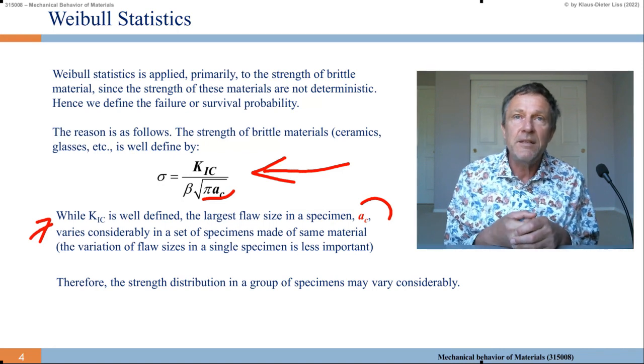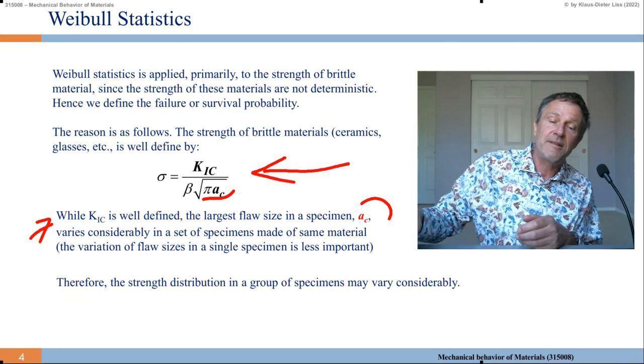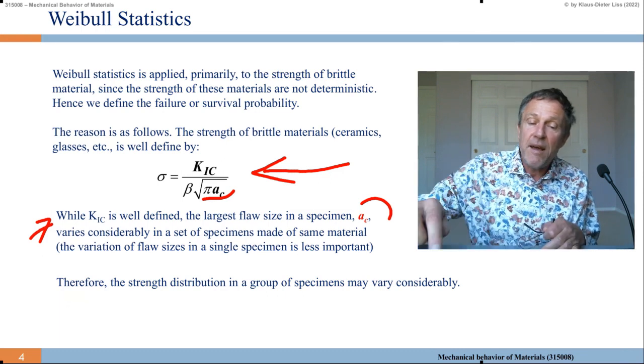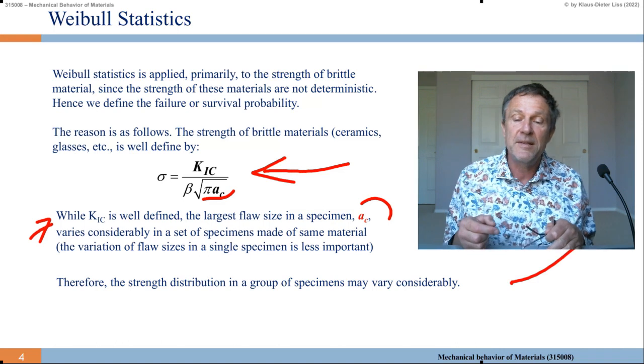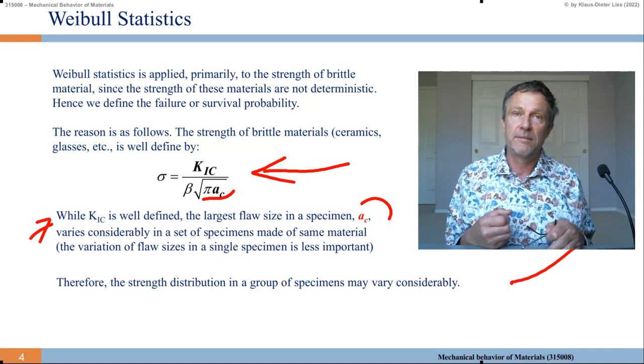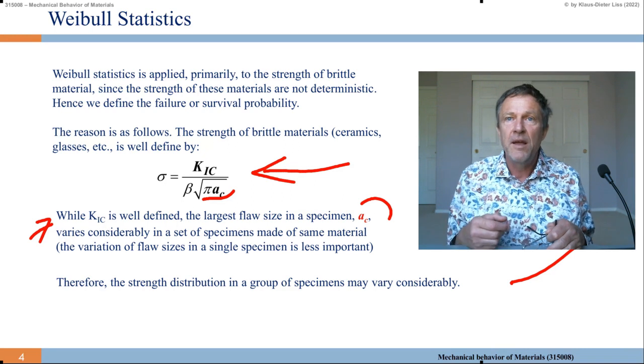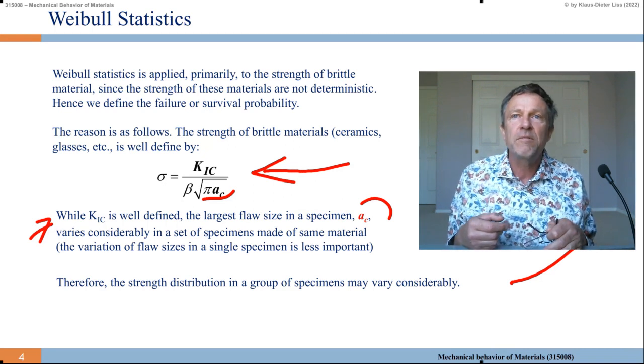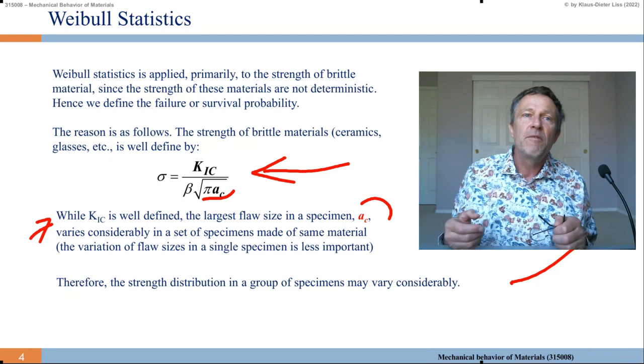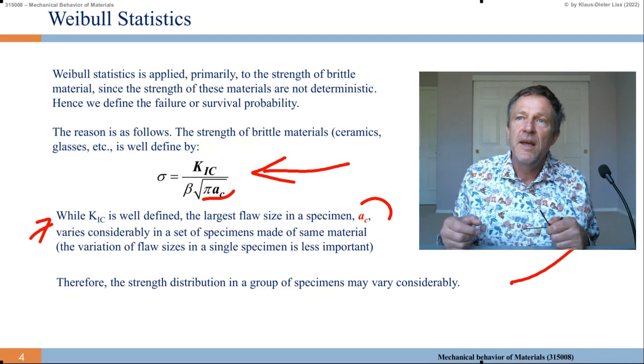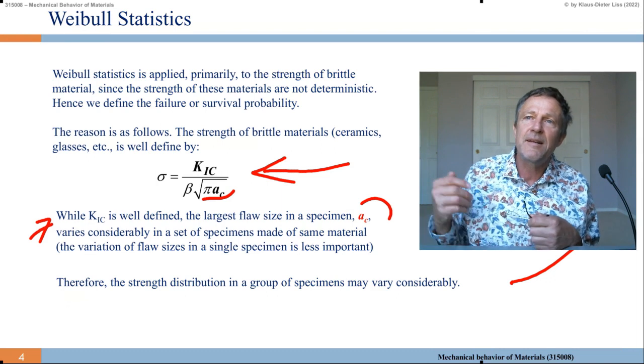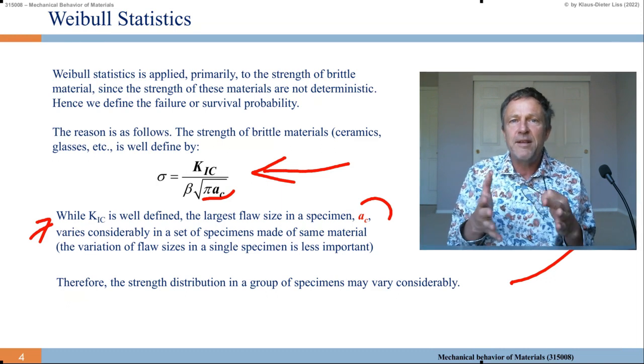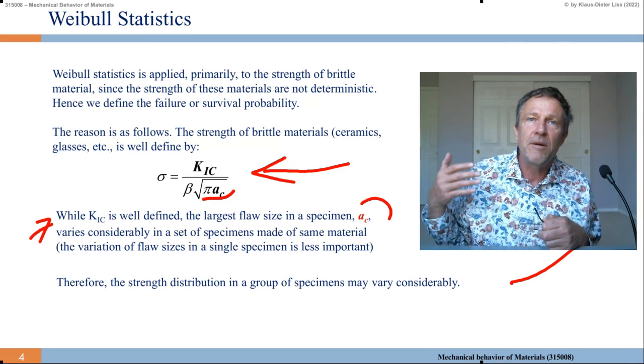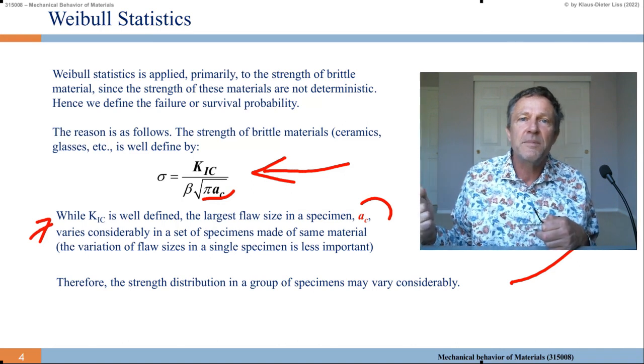So the size of these flaws, they may have some distribution, and also it depends critically, one over square root a_c, on that crack size, flaw size. So therefore, the strength distribution in a group of specimens may vary considerably. With many specimens, particularly a group of specimens from a class of materials, like say window glass, which is made by one company and by another company, and they make it slightly different. The one works a little cleaner, the other not so clean. I know there are standards, but even in these standards there are some variations, depending on the day, on the production process, on the dust which comes in, and so on.